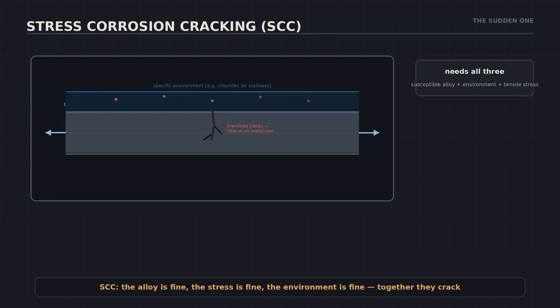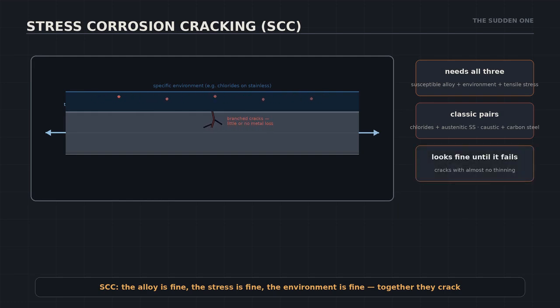Stress corrosion cracking is the sudden one. It needs all 3 at once: a susceptible alloy, a specific environment, and tensile stress, from service or left over from welding. The classic pair: chlorides on austenitic stainless steel, and caustic on carbon steel. The result is branched cracking with almost no metal loss. The part can look perfect and fail the same day.